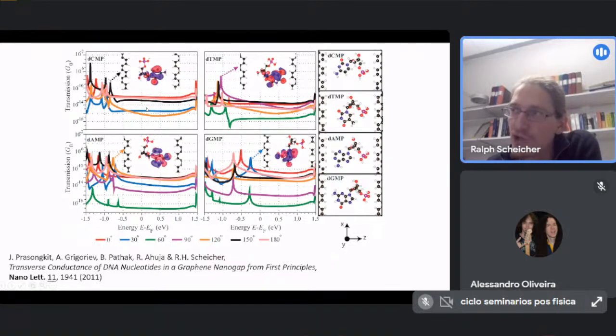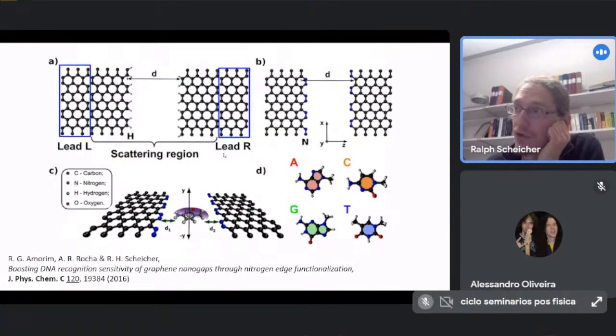And if you then integrate underneath these curves, the area under the curve can give you an idea for the current that you can obtain there. And so the conclusion from this paper was that, yes, you can basically distinguish the 4 different bases, but there's some overlap in the current.